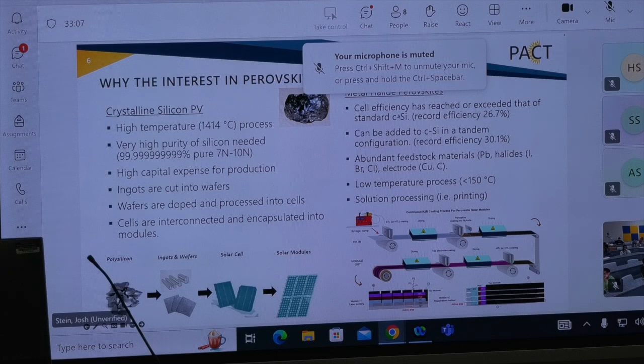So in contrast, metal halide perovskite solar cells are made using very abundant materials: lead, and halides, which include iodine, bromine, chlorine. They're very abundant. They use electrodes that are either copper or even carbon electrodes like graphite, and it's a very low temperature process. It's less than 150 degrees C most of the time, which is just a little bit above boiling temperature.